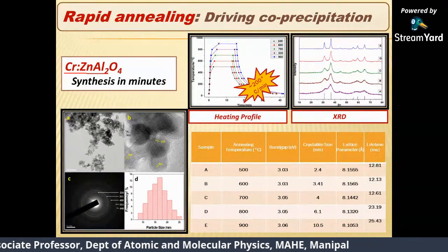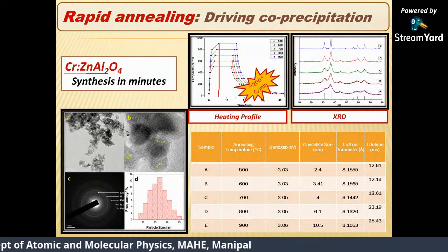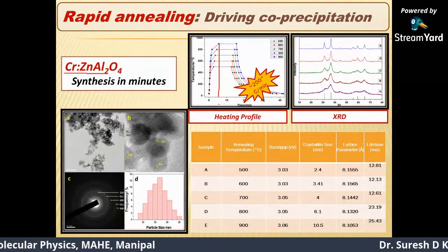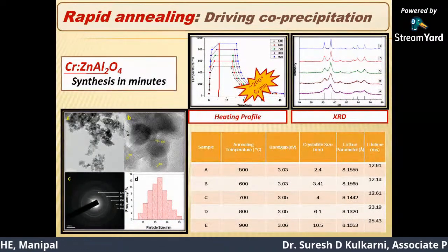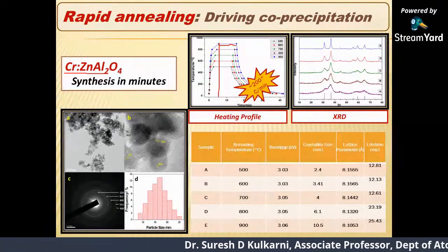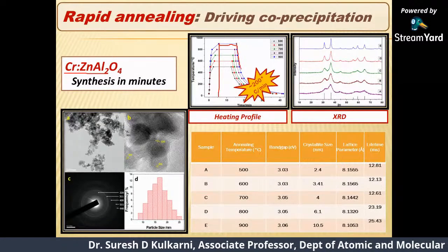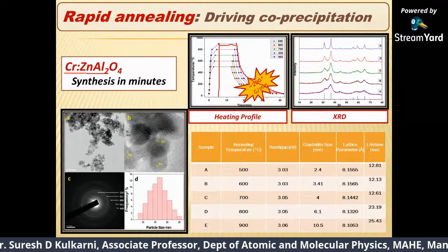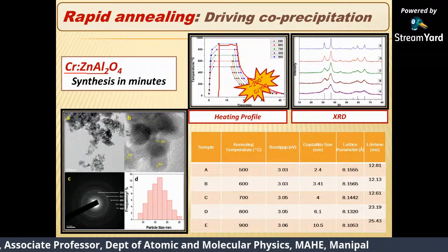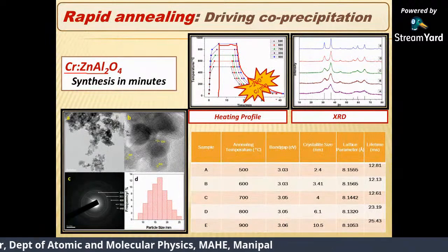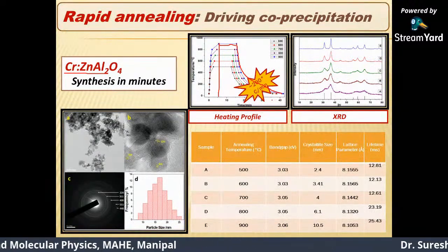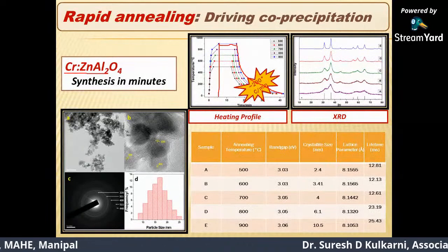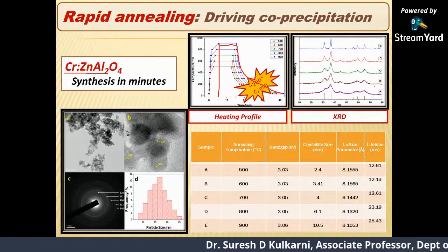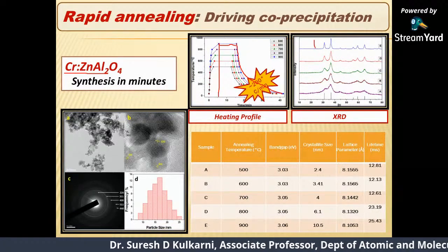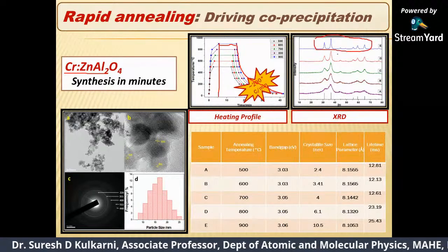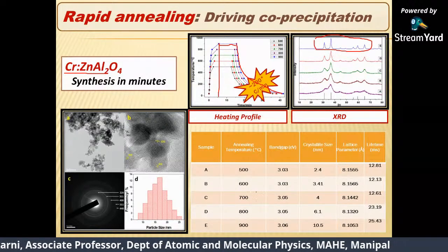Okay, so at this time you can see in 4 to 5 minutes I can reach 900 degrees Celsius, and I can maintain the 900 degrees for the time that I want, and then you see the material is rapidly getting cooled. So altogether, start to end, within about 40 minutes I have done the entire processing of synthesizing and annealing. Okay, so when I do an XRD pattern, you can see that within 40-50 minutes I have made nicely crystalline material.